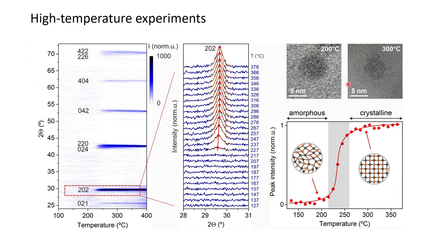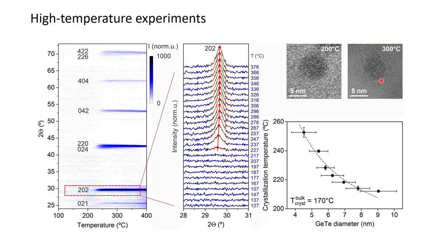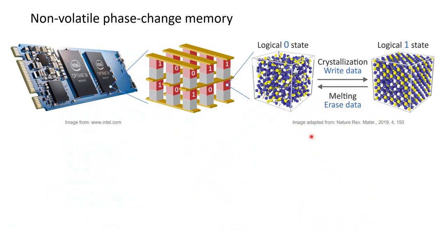We also have a supplementary TEM measurement showing that the material has no atomic arrangement up to about 200, and already at 300 it has a very clear atomic arrangement. Luckily, this property is size dependent, and then we can find the size dependency of this crystallization phase transition, and then we can find a very good, very promising application for this phenomenon.